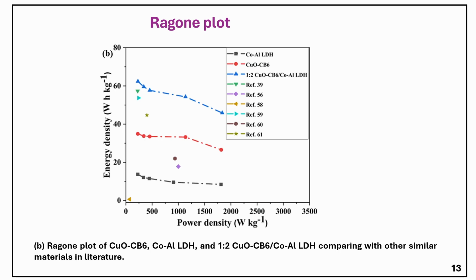Next, coming to the Ragone plot. This Ragone plot was also used to show the relationship between energy density and power density for all the materials. At a current density of 0.45 ampere per gram, the nanocomposite achieved a higher energy density of 63.87 Wh kg^-1 and a power density of 114 W kg^-1. For comparison, at the same current density, pristine CuO-CB6 recorded an energy density of 36.30 Wh kg^-1 and cobalt aluminum LDH showed an energy density of 15.04 Wh kg^-1. These results confirm the superior performance of the newly synthesized 1:2 nanocomposite compared to similar materials reported in the literature.